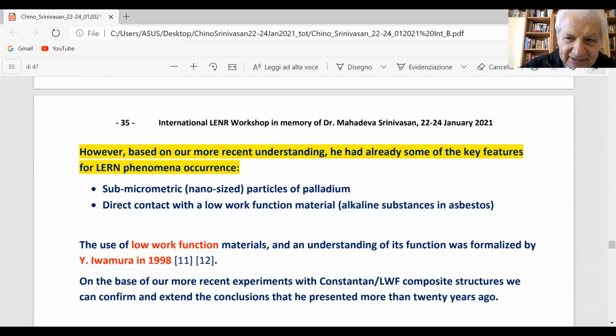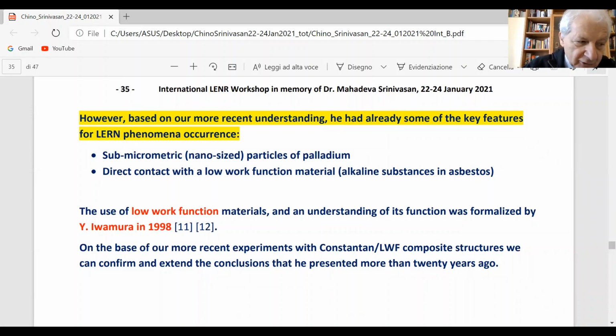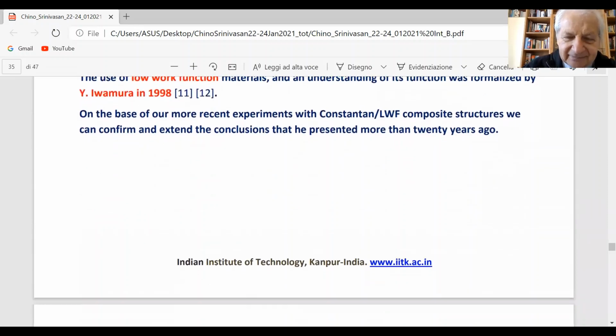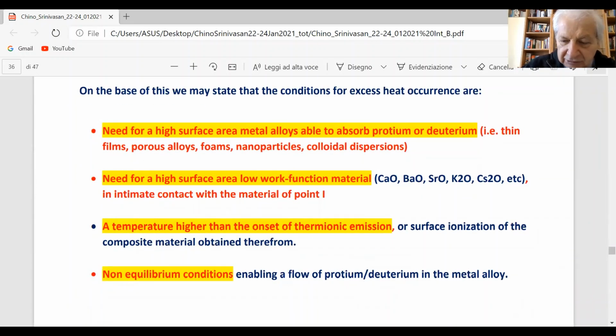In our case, we make some progress. We have controlled micrometric and nanosized particles, palladium before and now constantan, and we have a direct contact with the low working function materials, meaning alkaline earth substances in the state of asbestos. The use of low working function materials in cold fusion experiments was pioneered by Iwamura since 1998 in electrolytic environments. Low working function materials are usually alkaline earth elements, oxides, calcium oxide, barium, strontium, or alkaline like potassium, cesium.